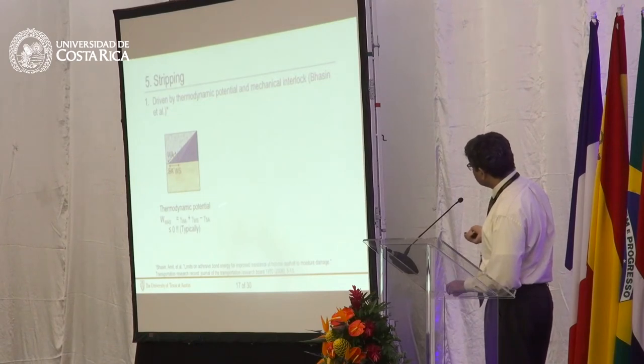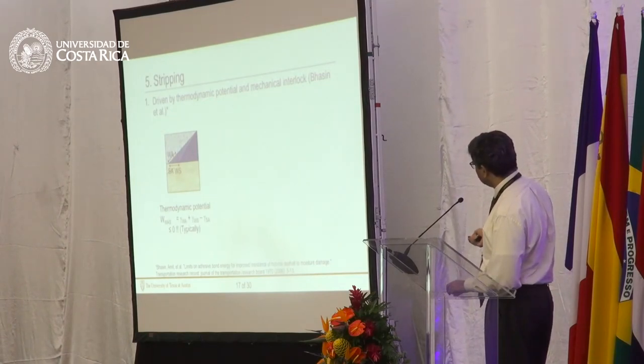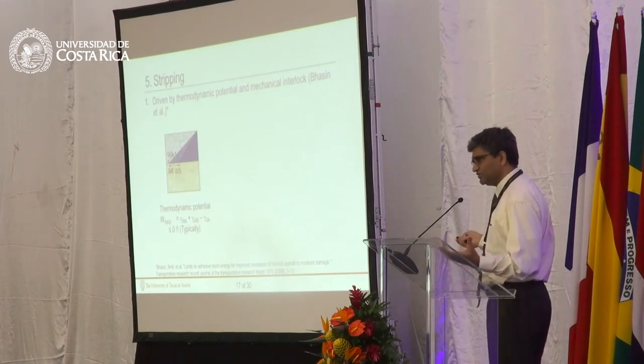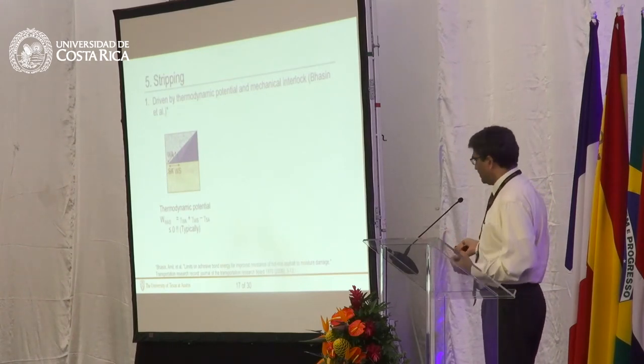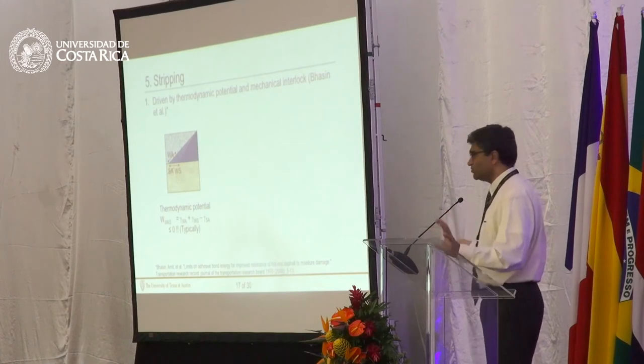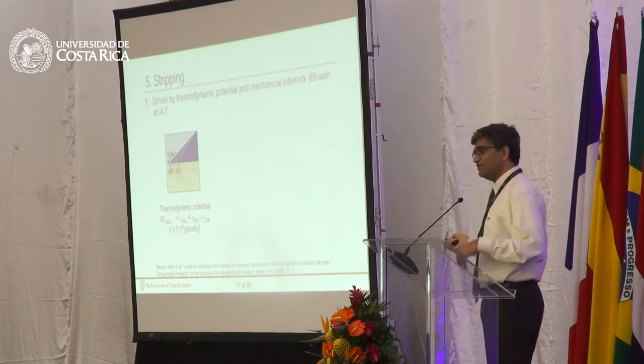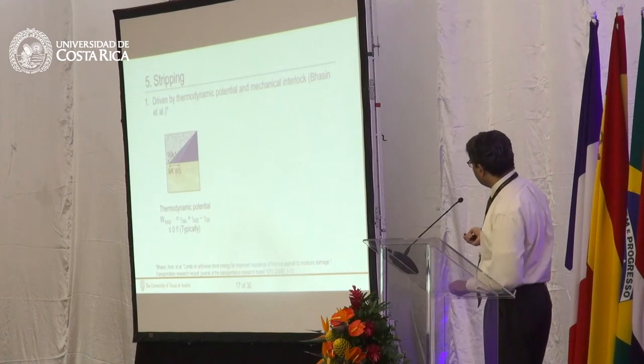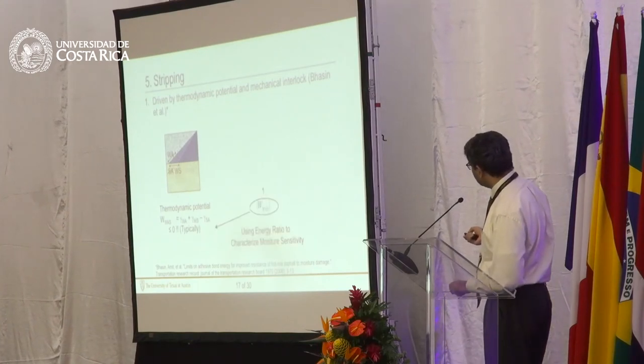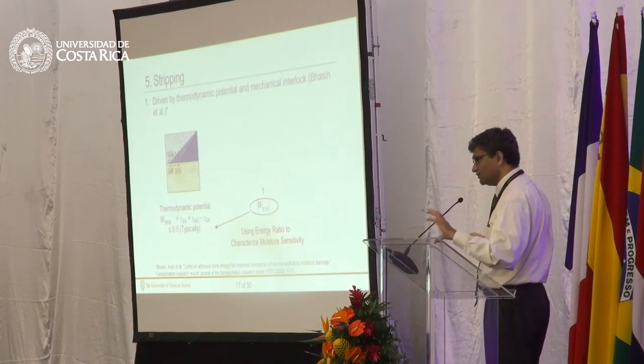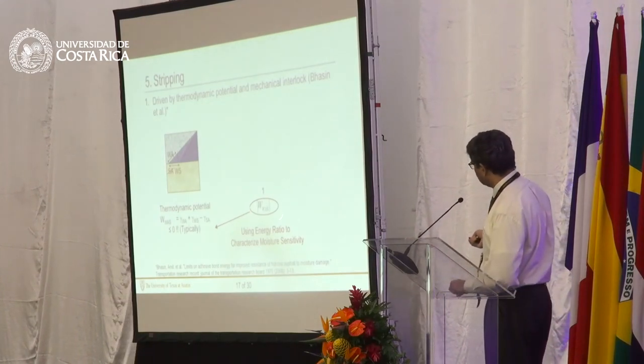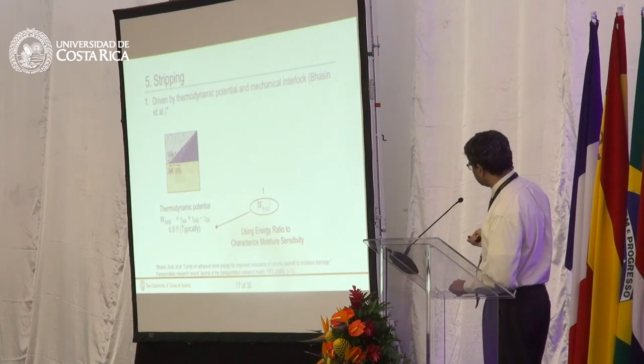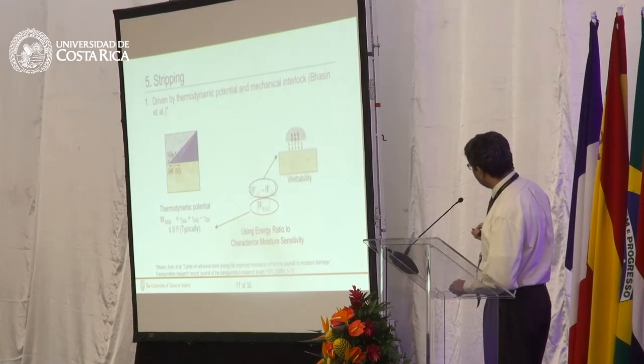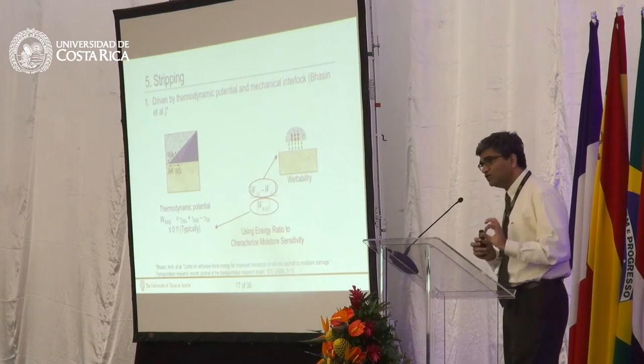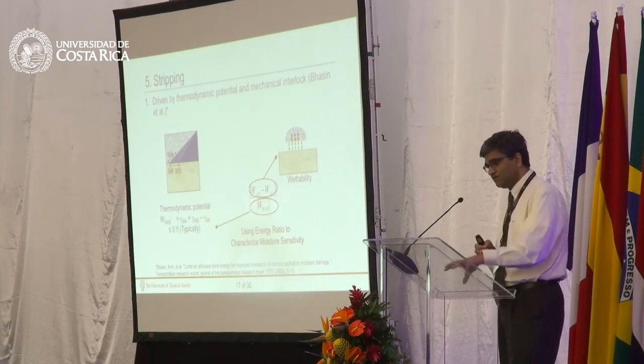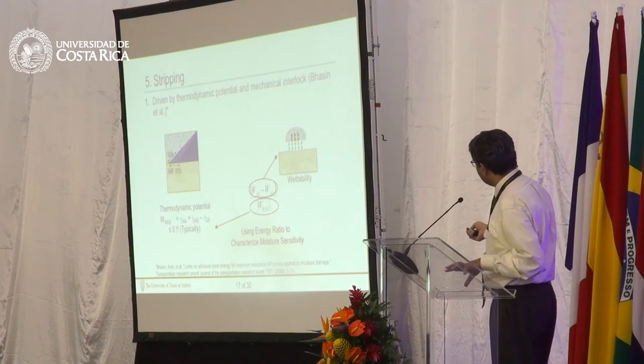You can measure surface energy of these three materials here, water, aggregate, bitumen, and you can calculate this energy transaction that takes place. And that energy transaction is less than zero, meaning thermodynamics favors going into this moisture damage configuration rather than not going there. So what we found out was that for material compatibility, this parameter should be as small as possible. We also looked at other factors like wettability, which is the competition between the molecules of the bitumen with itself versus the surface beneath it. And that parameter is right here.